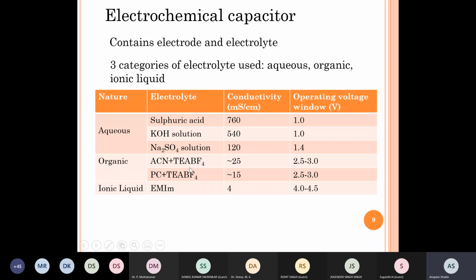Organic electrolytes, so acetonitrile with TEABF4, which is tetraethyl ammonium tetrafluoroborate. That is a salt and ACN is a solvent. The conductivity of organic electrolyte is much smaller, very poor, because they are large molecules. Both the solvent molecules and the ions themselves are large. So BF4, for example, will become the negative ion, and TEA will become the positive ion. Both of them are very large compared to a sodium ion or a proton. However, they provide a much higher operating window, 2.5 to 3 volts. So from an energy density point of view, mostly it is organic solvents which are used in supercapacitors.